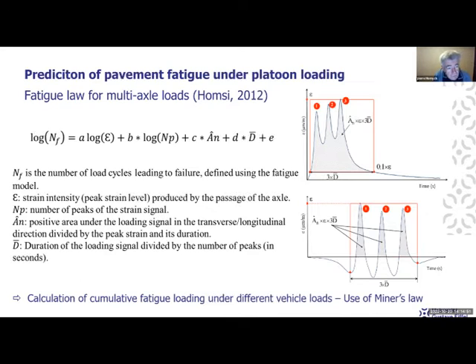And for that, we used a fatigue model for multi-axle loads, which was developed in our laboratory a few years ago by Homsi. The normal fatigue law, which is used in the French pavement design method, relates the number of cycles to failure only to the maximum tensile strain. And in this multi-axle fatigue model, you have 3 other parameters. Parameter NP, which is the number of peaks of the signal. The parameter AN, which represents the surface of the signal, let's say the average strain intensity, and D, which represents the duration of the strain signal.